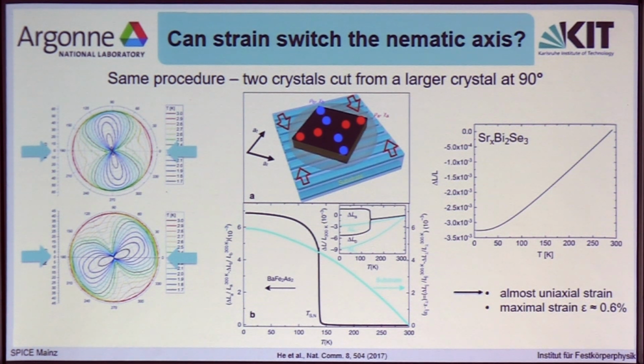And so if you were to mount your samples on here, they would experience a very anisotropic strain along one and the other direction. Now, comparing with the thermal expansion of strontium-doped bismuth selenide that you can see here on the right, you will realize that the thermal expansion of strontium-doped bismuth selenide matches quite well the low contraction direction of the glass fiber reinforced plastic. So we will treat this as almost uniaxial compression along this other direction.